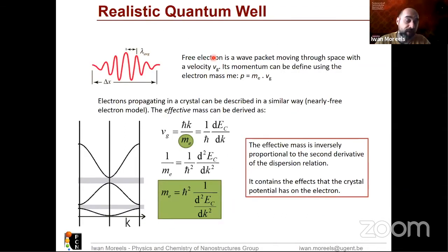So this is the first effect, which is modifying the band gap of the material. And in the very strong confinement regime in which we are working, because these platelets are only, say, 1 to 3 nanometers thick, you have this leakage and a reduction of the square dependence of the band gap on the thickness.